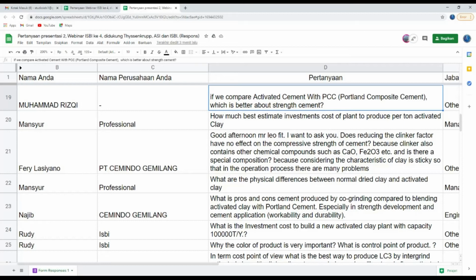What are the physical differences between normal dried clay and activated clay? The difference is that standard clay typically has quite a high amount of clay minerals in it which are not active. What I wanted to show you on my slide 11 is that in the raw clay there is a certain kaolinite content which is not active. So it is not contributing to the strength development. We want to make the kaolin active, and this is why we are activating it. So the difference is that in the raw clay there is not that much active material as in the activated material. So at the end, you are able to replace more clinker with activated clay compared to raw clay.